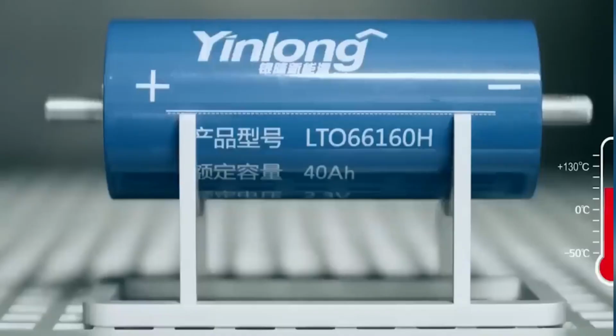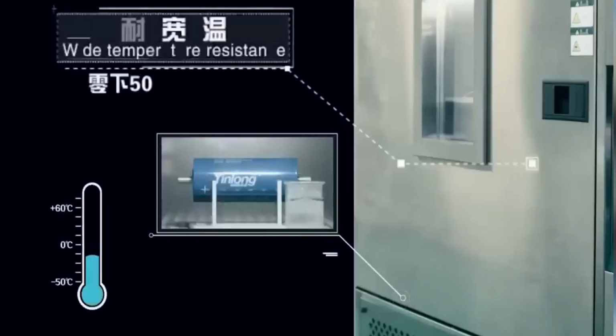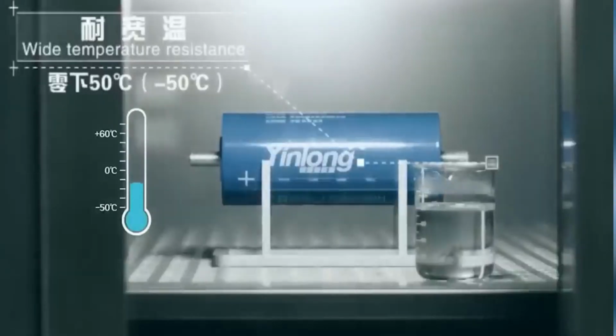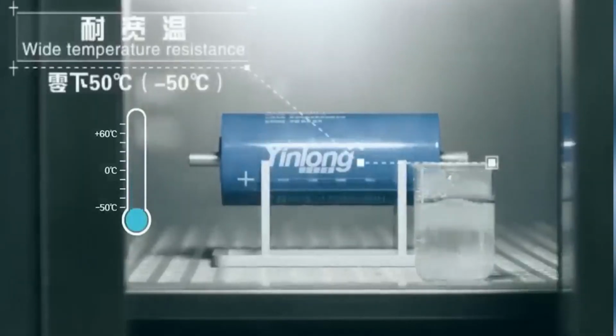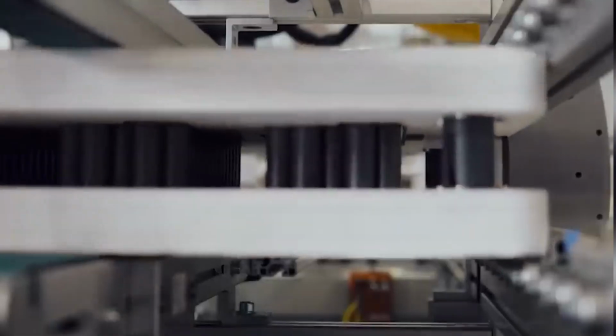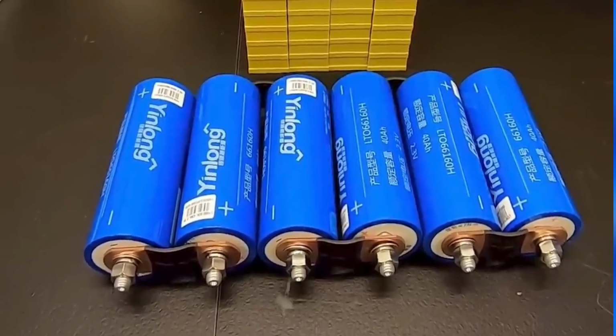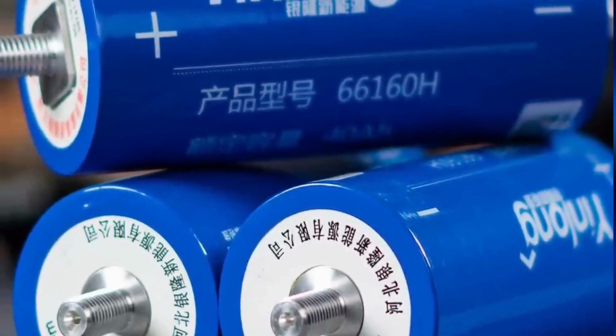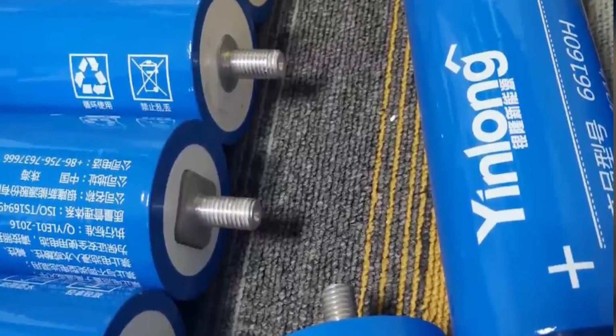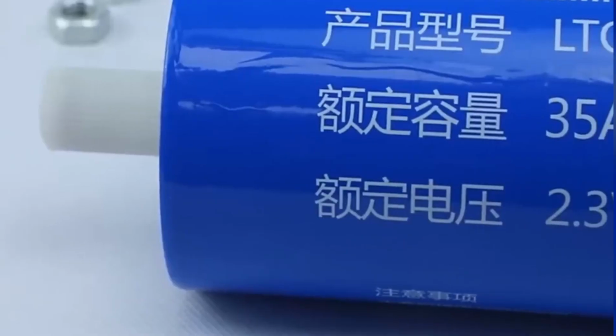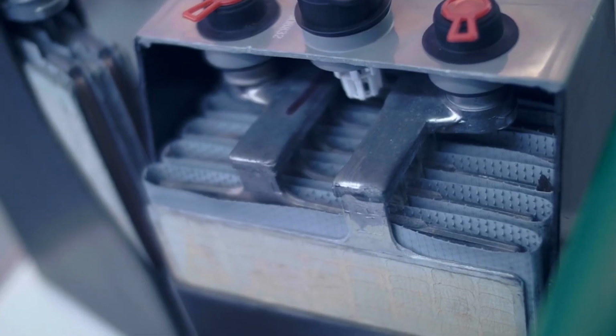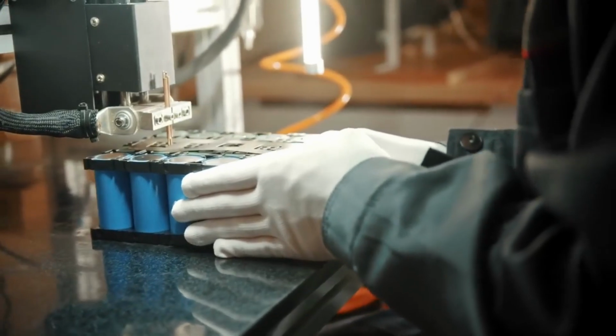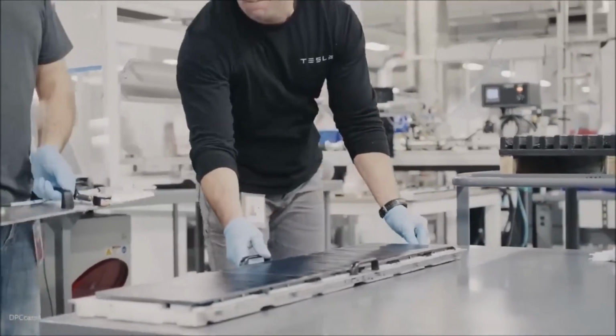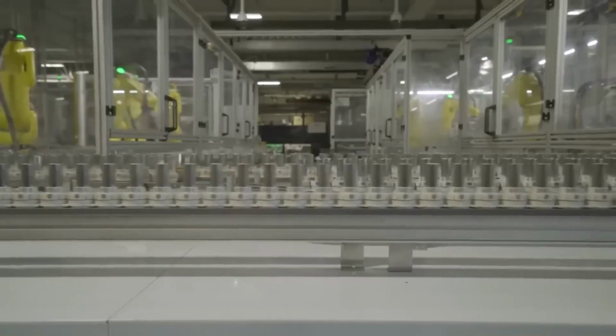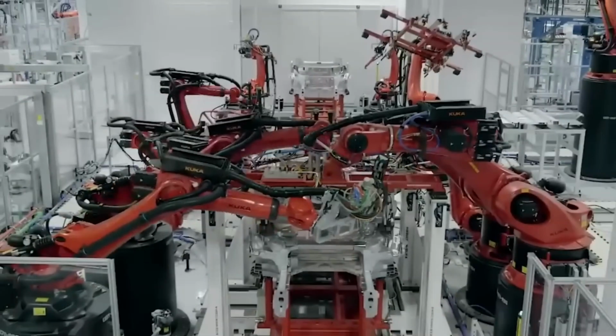While many batteries struggle in cold conditions, LTO cells continue to operate seamlessly even at negative 50 degrees Celsius. Specially designed products can even operate stably at this extreme temperature without being affected by the environment. At such low temperatures, the lithium titanate anodes in LTO batteries defy the tendency to cause short circuits or aggravate anode dendrites during charging, a feat that is not achievable with graphite anodes. This enables LTO batteries to be rapidly charged and discharged in diverse settings, making them particularly well-suited for automotive applications.